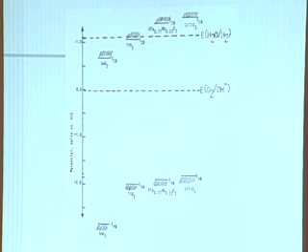So that was okay. My favorite material, though, is this material right here, strontium titanate. Very underutilized. It's not really good in the sense that on the Earth, we don't have a lot of photons that are that big, and you notice you're throwing away an awful lot of that energy. But it does straddle the band edges. So if we happen to live on, say, the moon, this wouldn't be such a bad material. We got more UV photons coming out. The band gap here is about 3.5 electron volts, a little less than that, 3.2 actually.